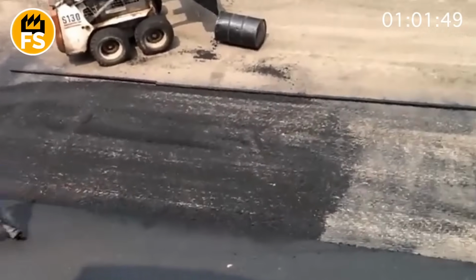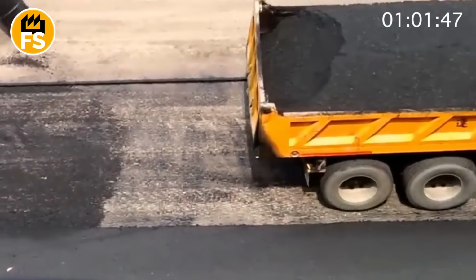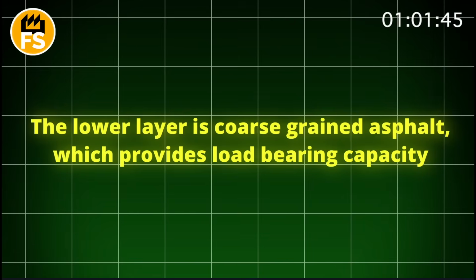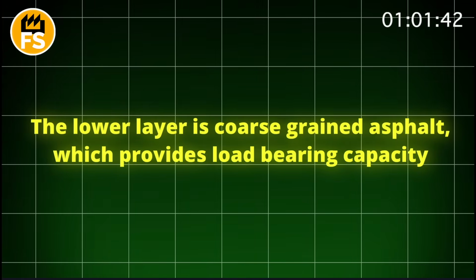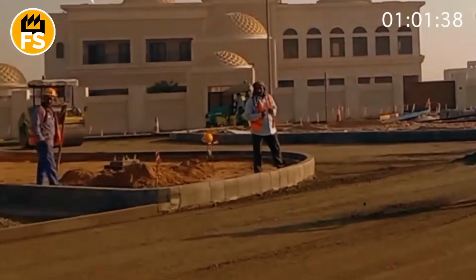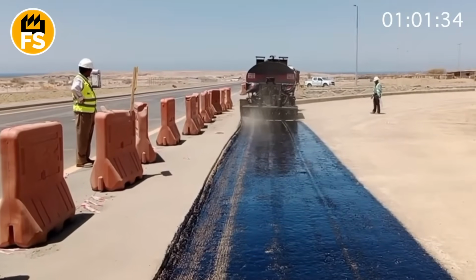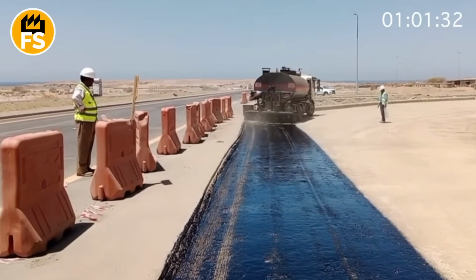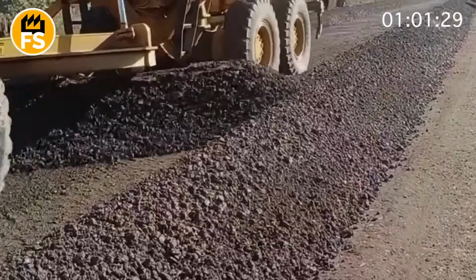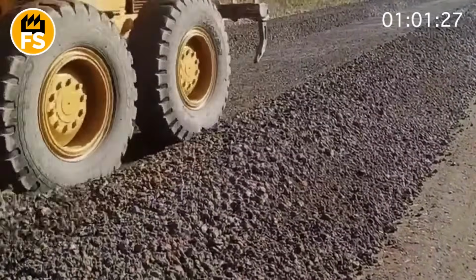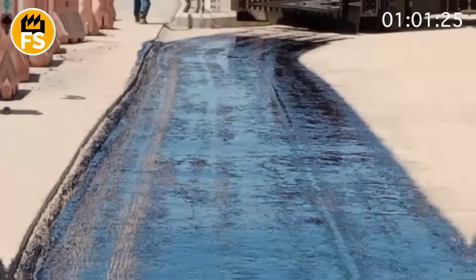A feature of Dubai's highways is that they have a multi-layer structure. The lower layer is coarse-grained asphalt, which provides load-bearing capacity. The middle layer is made of modified bitumen, which acts as a shock absorber. The top layer is a thin layer with a polymer coating, which provides grip with the wheels and resistance to abrasion. In some cases, light reflecting minerals are added to reduce surface heating.